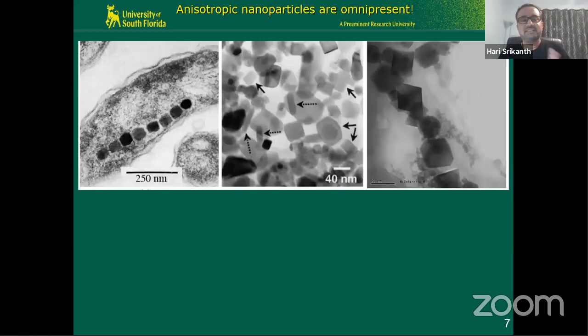Okay, so it turns out that anisotropic nanoparticles are actually a lot easier to make. It's actually very hard to make a perfectly symmetric nanoparticle, okay? So it's a lot easier to make anisotropic nanoparticles, and not only that, anisotropic nanoparticles are omnipresent. They're around everywhere. And just to illustrate this, I'm going to show you 3 TEM images. That's what they are, transmission electron microscope images. And it's the same material, iron oxide, magnetite, Fe3O4, or the variations of iron oxide, different ferrites, spinel ferrites, okay? That's the only material here.